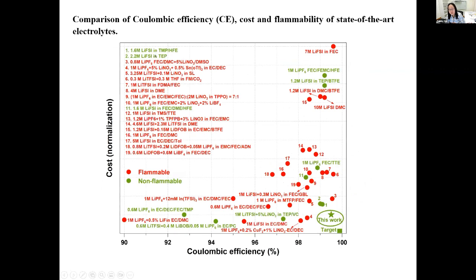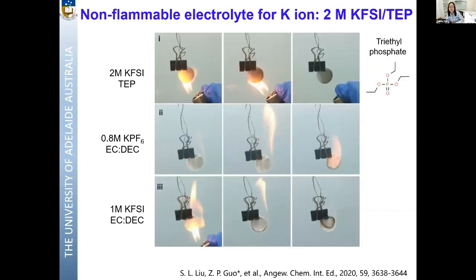You can see the green color means non-flammable, the red one means flammable. And you can see our electrolyte exhibits one of the best Coulombic efficiency with a low cost, because lithium nitrate is relatively cheap. So this is a non-flammable electrolyte we developed for lithium-ion battery.